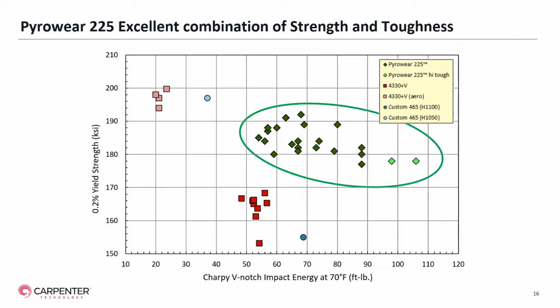mid 160s. Our custom 465 alloy, given an H1100 or H1050 age, are given as the blue dots, either the dark blue as the H1100 or the light blue H1050. But you can see that the trade-off is fairly typical in these structural type steels, where you're either offering high yield strength and relatively low toughness, or high toughness and low yield strength. What we're excited about with Pyrowear 225 are the green diamonds given circled, as you can see, where we're offering both high strength and high toughness